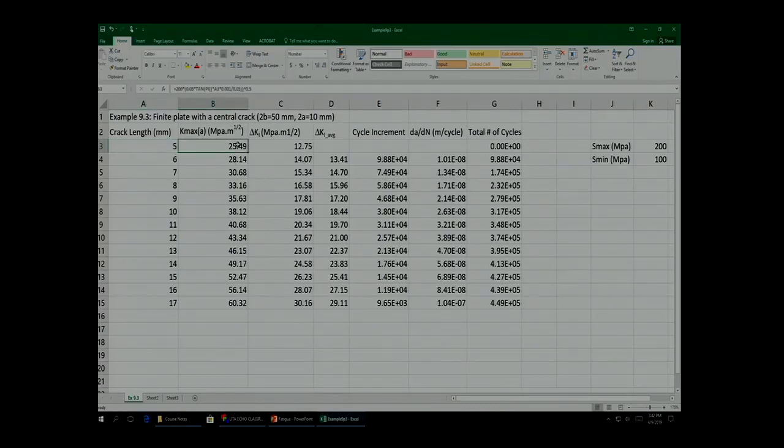If you look at the formula there, it's just the equation I wrote down, and then calculate the K max. Now I can see that if my K_IC is 60, I have it over here. At 17 millimeters, I just cross 60, right? So that means my a_C is going to be very close to 17. So I just take those two numbers.